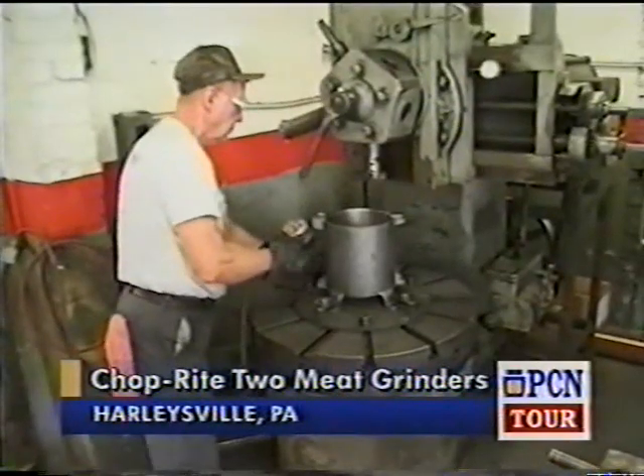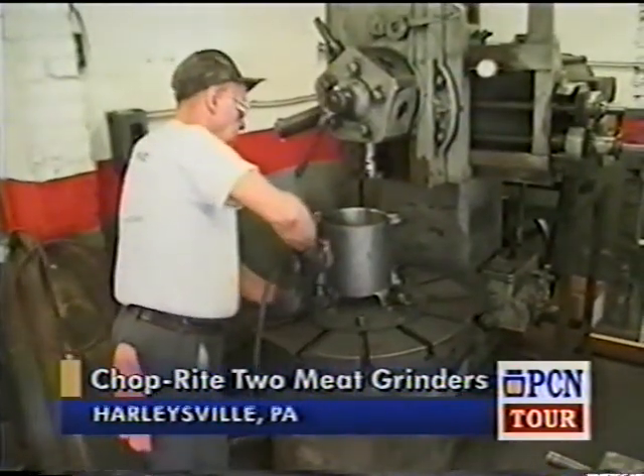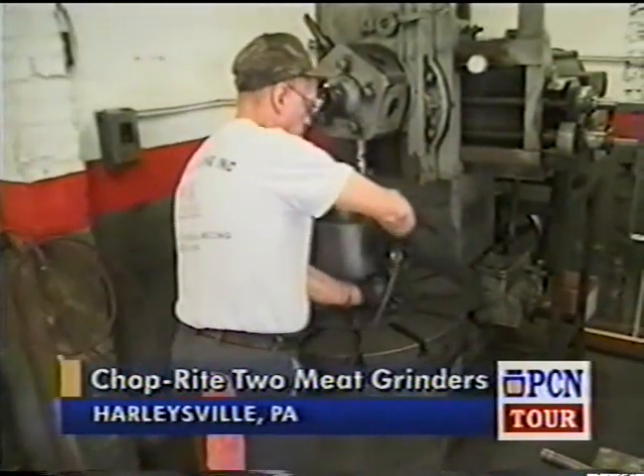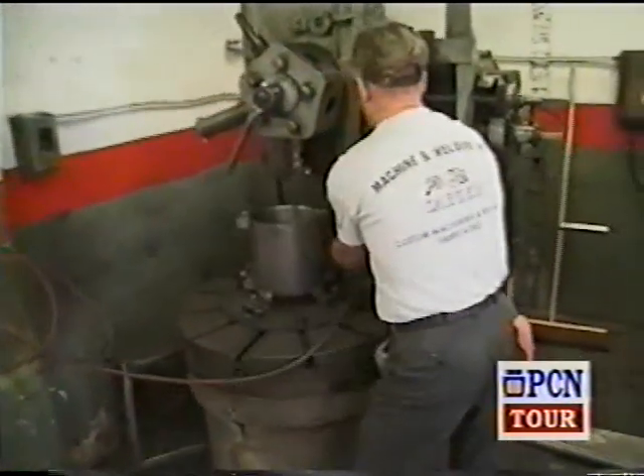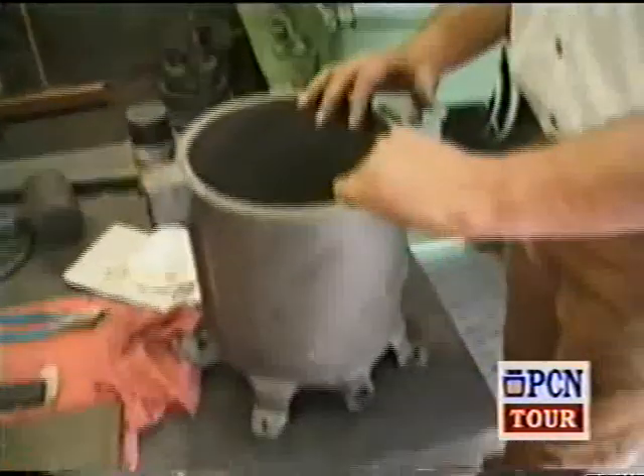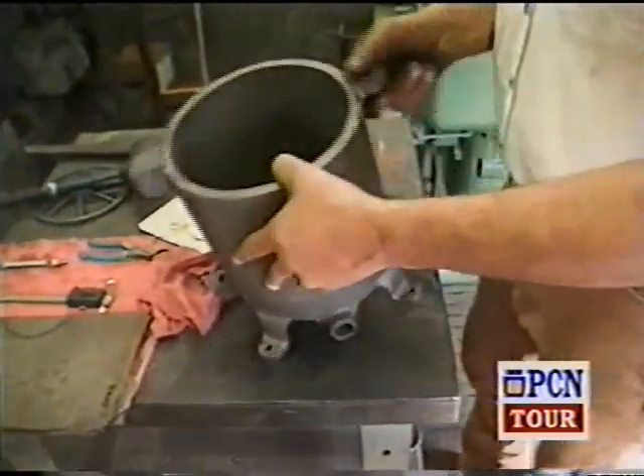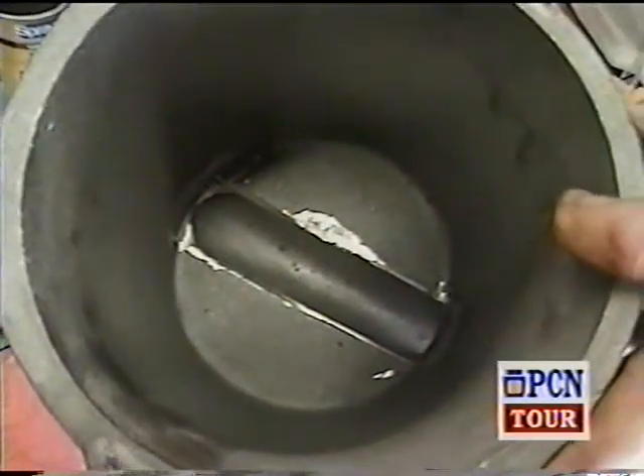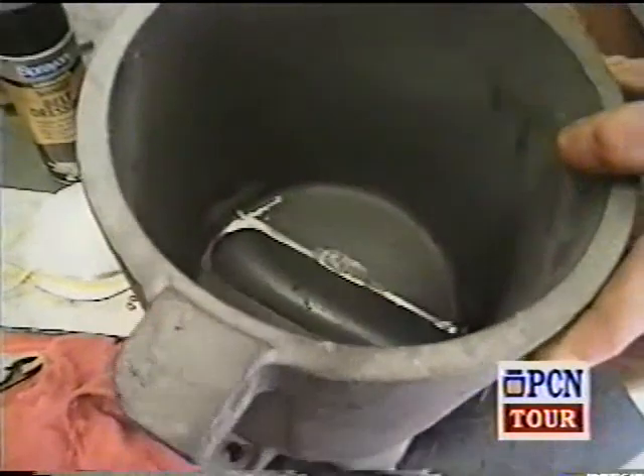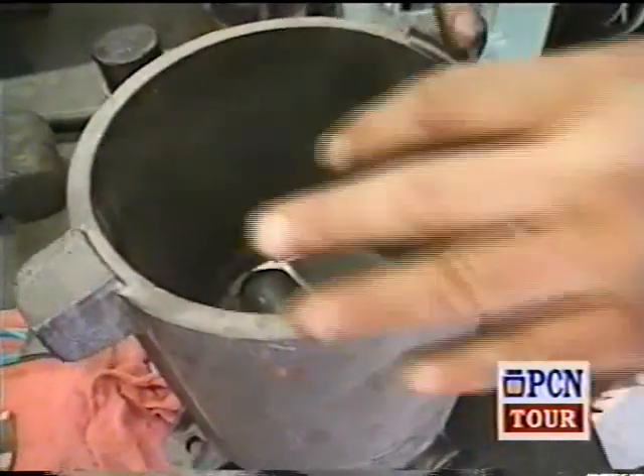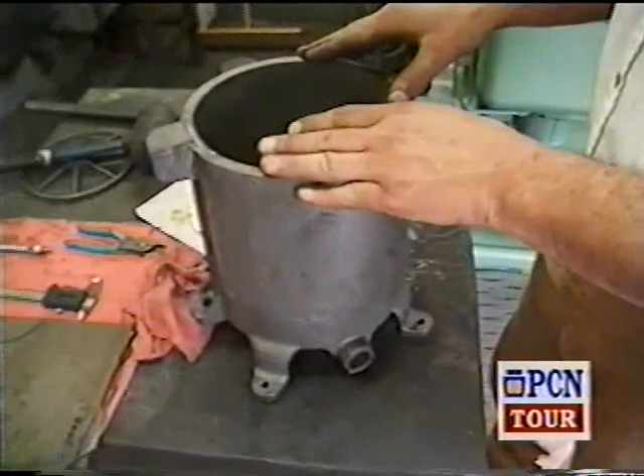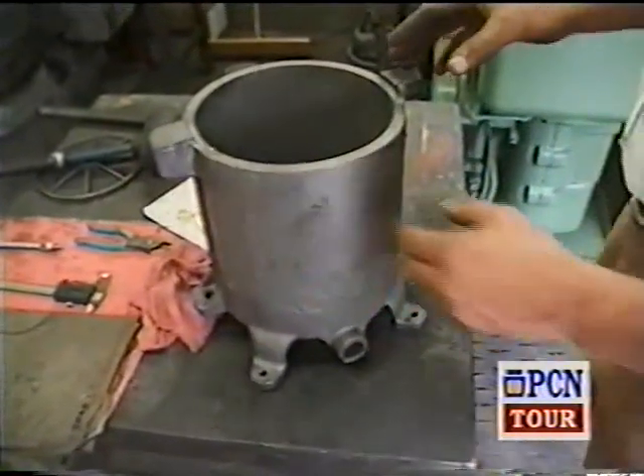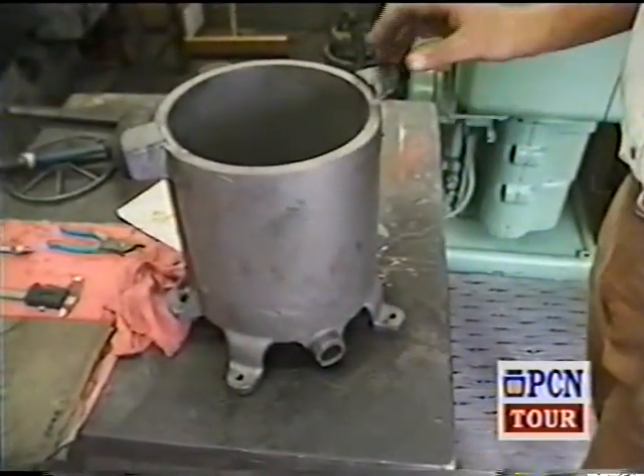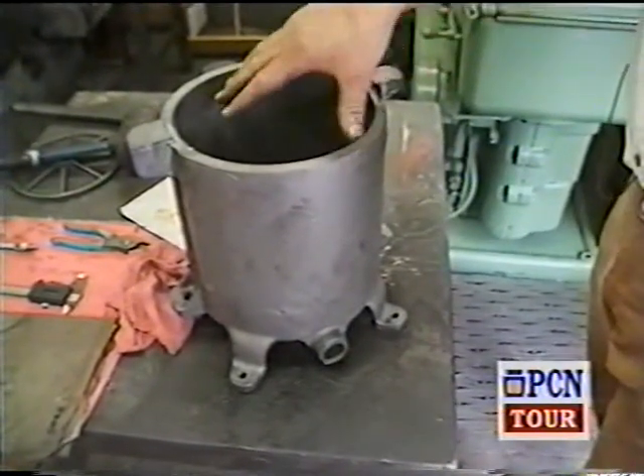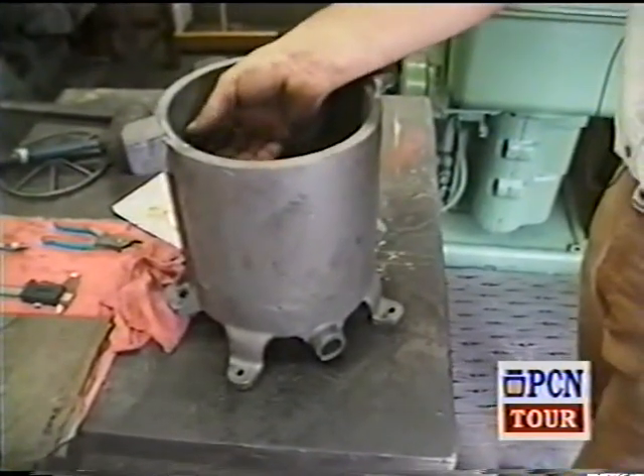Back at the boring mill, this is where we bore out the 35 stuffer. As he's taking one of them off, we can look at a raw casting that came from Ephrata. You can see how the inside looks before we bore it out. This operation is critical because the bore has to be true and to size, so when the top arch and the plunger plate goes in here, we only have to have a couple thousandths, roughly 3 to 5 thousandths clearance on the side, so the meat does not ooze up and around.